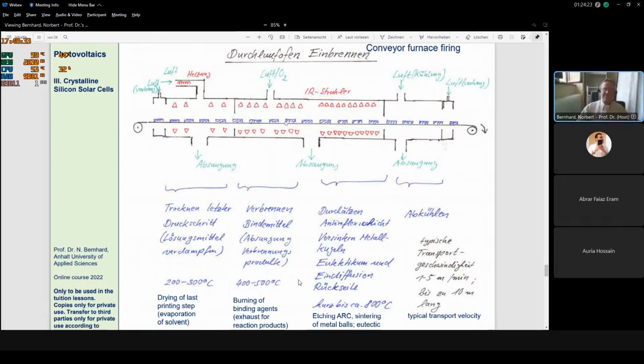In the first step, between 200 and 300 degrees centigrade, we are just drying the printing step, and in fact it's 3 printing steps. Of course, it's clear it's 2 for the front side, for the back side, but on the back side we have, in addition, to print some solder pads because aluminum cannot be soldered. Therefore, in total, it's 3 printing steps. That means in the first step, and of course these first 2, they are done for every printing step.